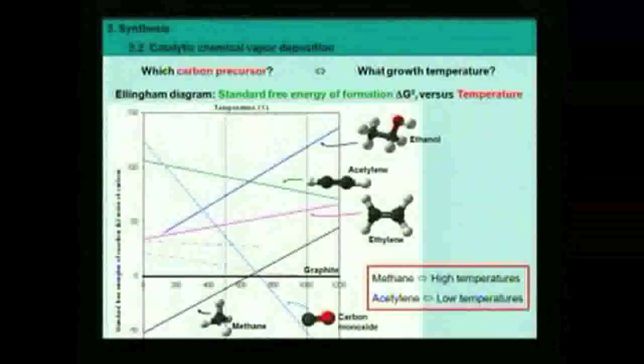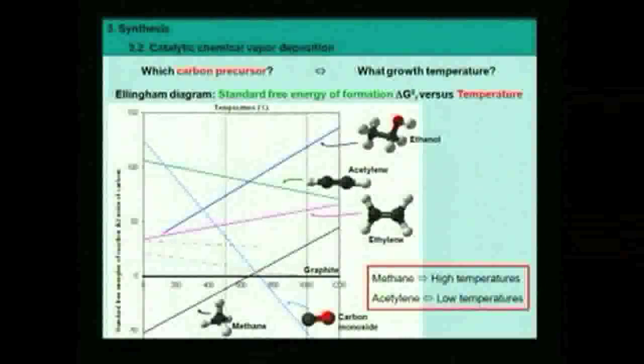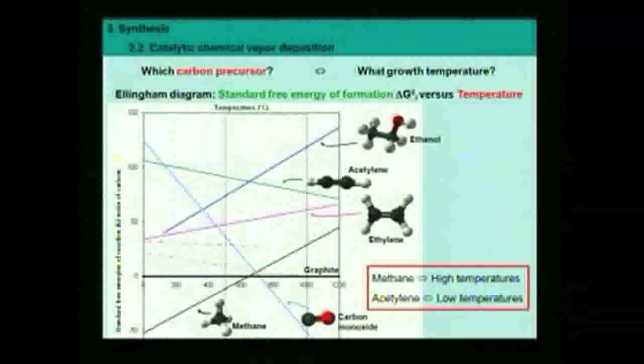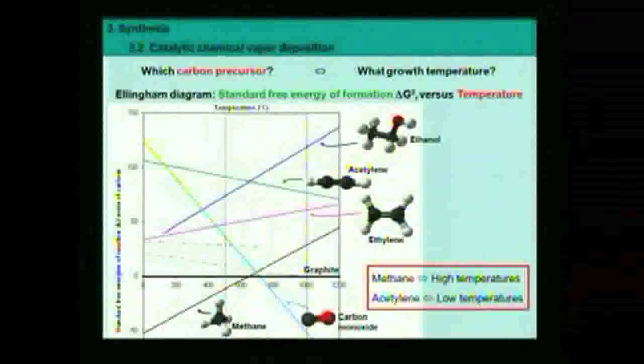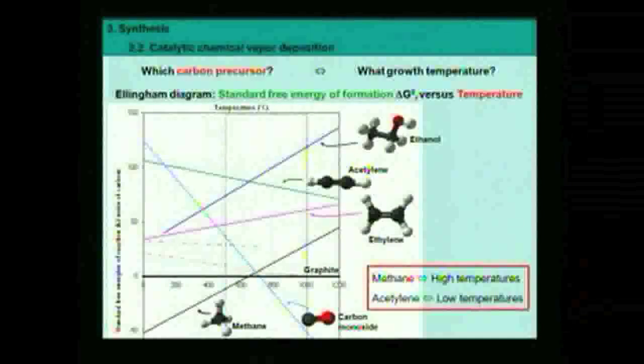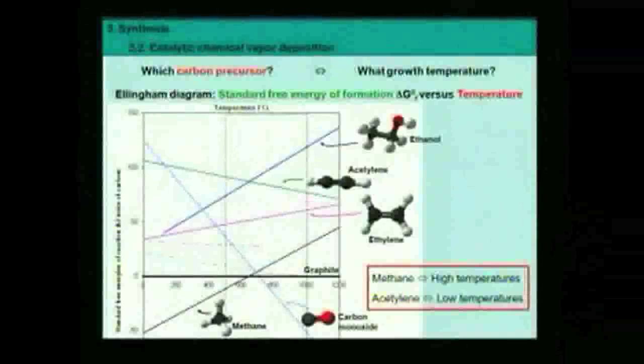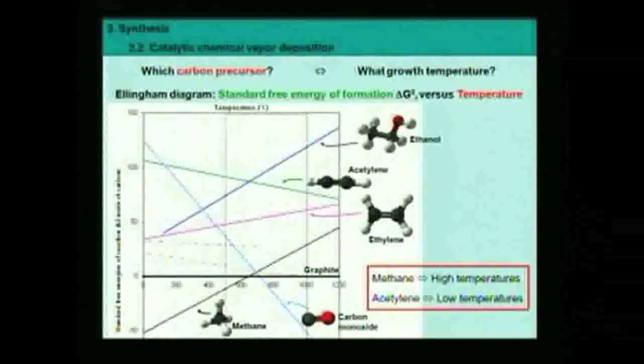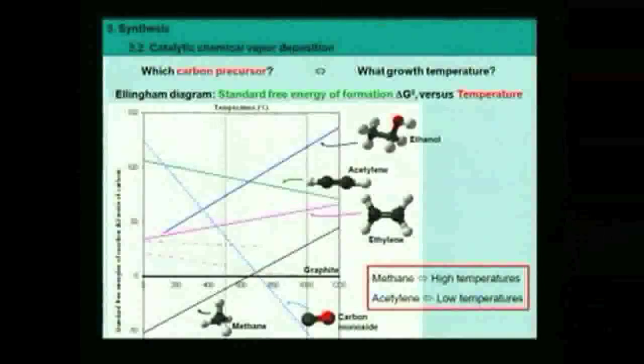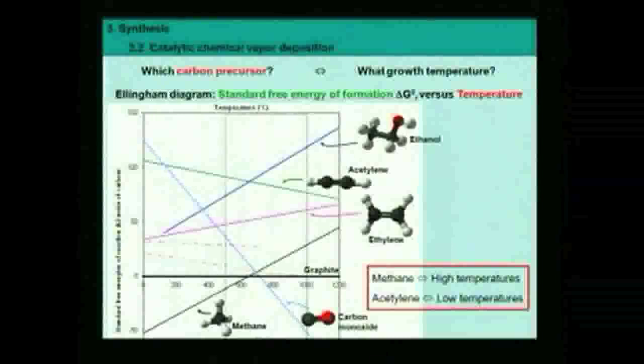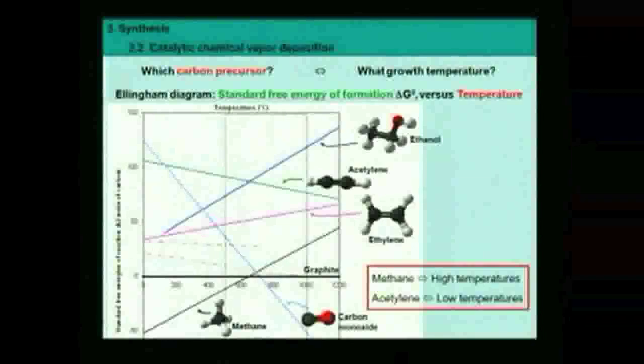Okay, so this helps to choose the proper carbon precursor, and as you can see, choosing the most appropriate carbon precursor is very dependent on the growth temperature you are going to use. And conversely, depending on the growth temperature, you will use a different carbon precursor. So this is the first Ellingham diagram. We will see others during the next slides. An Ellingham diagram is simply plotting the standard free energy of a reaction, often of formation, as a function of temperature, to know if a compound is more stable than another one, if a reaction is allowed, such things.